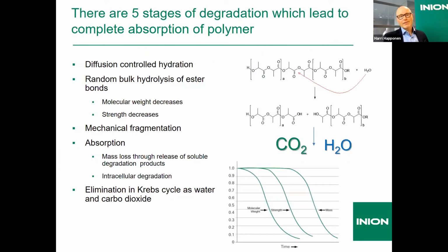Here you can see the 5 stages of the degradation of the implants. So the first is that the water is absorbed in the body and in the implant, and that's called hydration. It will happen during the first 24 hours basically. So there is water molecules everywhere in the implant, and thereafter the water will start breaking the polymer, and the molecular weight of the implant start decreasing.